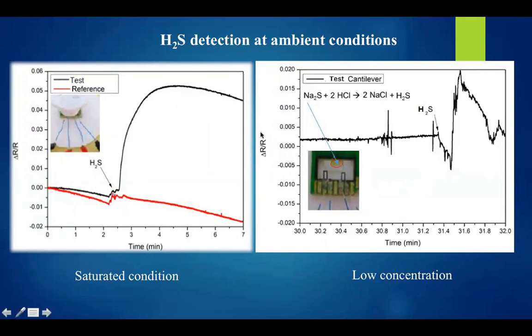So when we had a low concentration scenario, where we put the H2S gas in an open atmosphere and the gas was allowed to diffuse in the surrounding air, the test cantilever in this case did show a response and recovery of the signal. And here we can say that the major mode of interaction is physisorption, and the material is quite selective to even the low concentration of H2S.